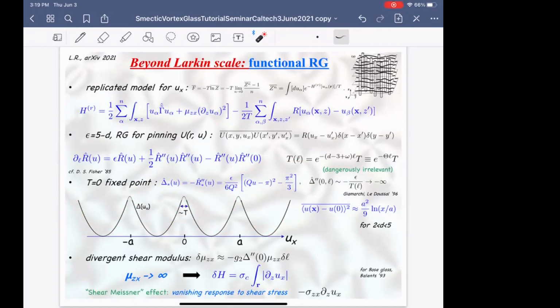Now, that's the flow of the random potential, but it turns out that these cusps are actually rounded by finite temperature. Even though the temperature is flowing to 0, it's dangerously irrelevant, so the cusps become sharper and sharper as the temperature flows to 0. So one can ask, what is the correction to this shear modulus in the presence of this random potential? The correction is proportional to the second derivative of this random potential. But since the first derivative jumps, the second derivative is infinite, so this has an infinite correction.